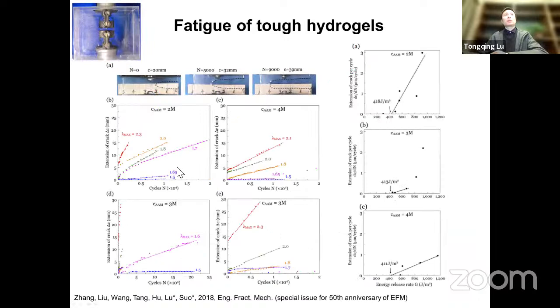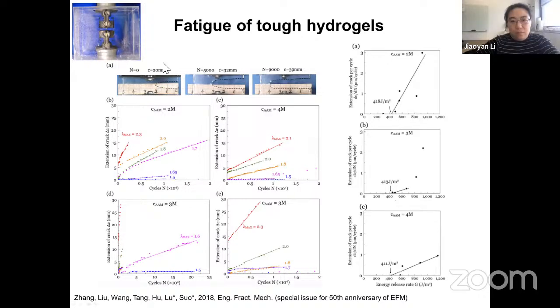So this picture describes how we do the experiments. If you are familiar with fracture mechanics, it's a very common practice. You just make a pre-cut and load it cyclically and measure the crack growth. This is the number of cycles, this is the extension of crack. Then you can plot the horizontal axis as energy release rate, and the vertical axis as the extension of crack per cycle. So then you can find the fatigue threshold.